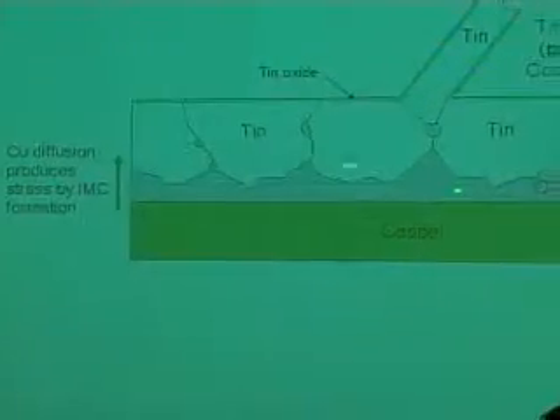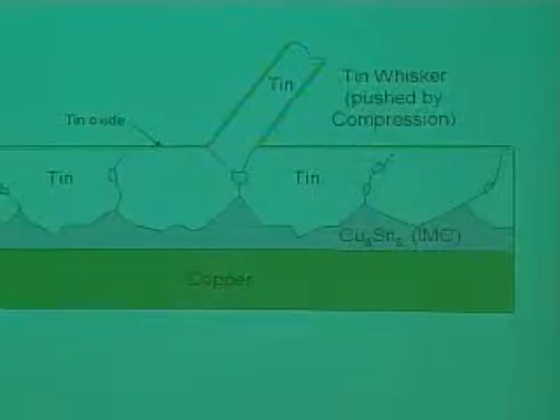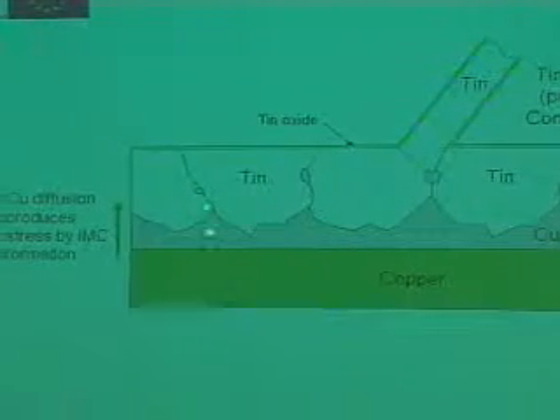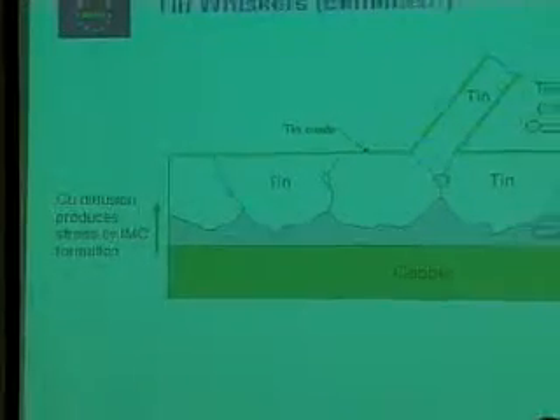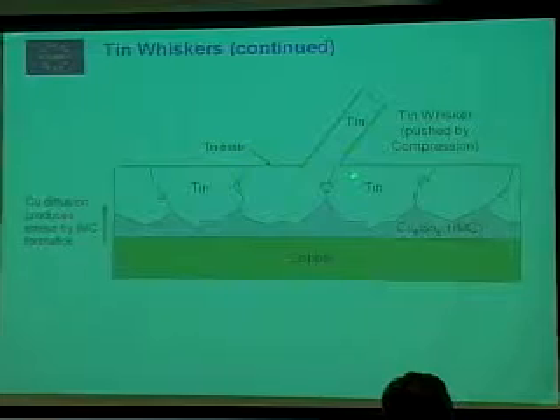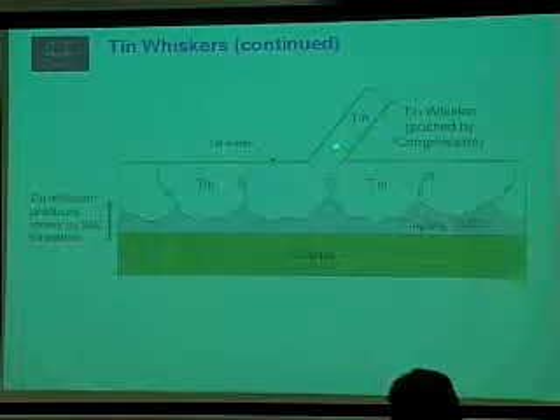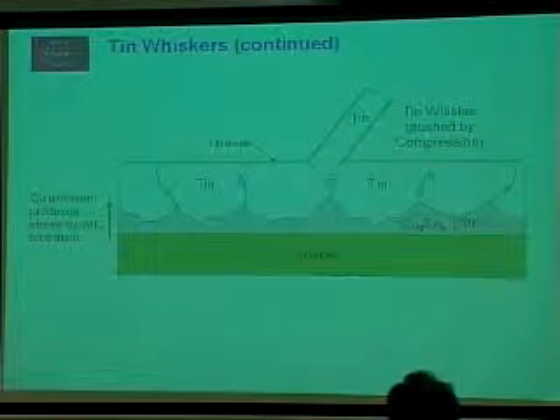And I think this is still somewhat debatable, but the model that I like is that, for example, we have a solder layer here that is tin-rich. It's on copper, and as the copper is dissolving into the tin, we're forming an intermetallic. And at the grain boundaries, we get enhanced transport, or we get regions that go deeper into the tin with the intermetallic. These grains of tin then are being pushed on or compressed or squeezed, and you'll have a tin whisker that will squirt out like toothpaste coming out of a tube. Fairly simple model. So it's actually being pushed by compression. And that's the model that I like. I know there are a lot of other models. There are some objections to this also, but it's a fairly simple model, and it seems to be about as good as anything that's been published.